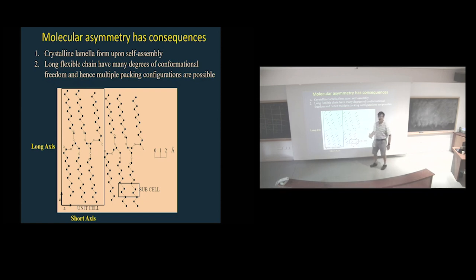In fats and oils, they don't characterize it fully, because it's so long ago, they based it on the long-chain alkanes. So they did a two-dimensional representation of the unit cell, and they call it the subcell. So all they're looking at is the reflections associated with the long alkane chains, which are very similar to long-chain alkanes, not the fatty acid per se. So nobody does indexing, believe it or not, in this area. You just look at the relative packing of the ethylene groups. And that is what defines alpha, beta prime, beta. You put it in the X-ray diffraction unit, you get the peaks where you are, and you get the number. Most people don't know what the number means, but it is the packing of these long chains. So the packing of the long chains defines the polymorphism.